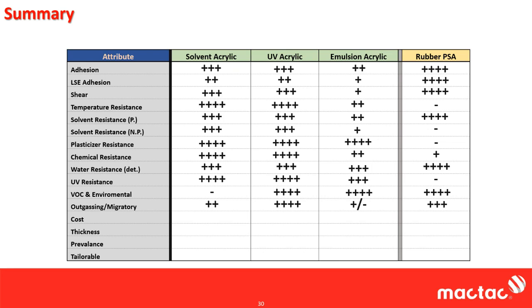And this is why. So this is the difference between VOC and outgassing. When you look at the cost, solvent acrylic is going to be the worst. UV acrylics too, actually emulsion acrylic, you can run them more efficiently, or you can run them at a higher speed, and the polymers themselves are a lower cost versus the UV acrylic. I will say as you start getting up and trying to push the top end of the emulsion acrylics, get up about 2 mils, then actually the speeds do inverse and UV acrylic can be run faster. But because of the cost of the polymer and how efficiently they do run, we'll rate them as a more cost-effective version than UV. UV is still worlds ahead of solvent, and here rubber actually kind of dominates that. Nothing's really cheaper than rubber.